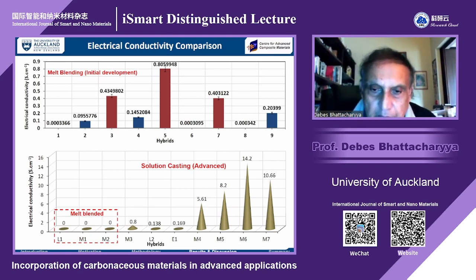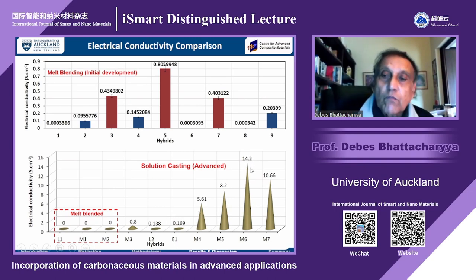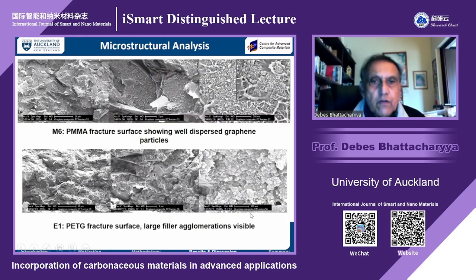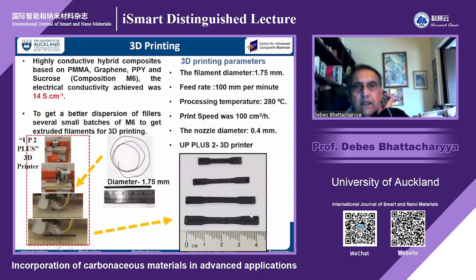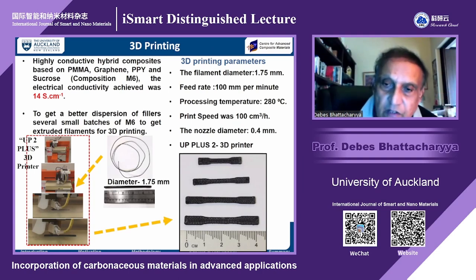So you compare the E1 result with M6, one order of magnitude higher, actually more than one order, 100 times higher. So two orders of magnitude better. So at least we got that. And then it had sufficient ductility that we could also produce these 3D printed wares. Not only that, these 3D printed dog bone specimens, these are also 3D printed.